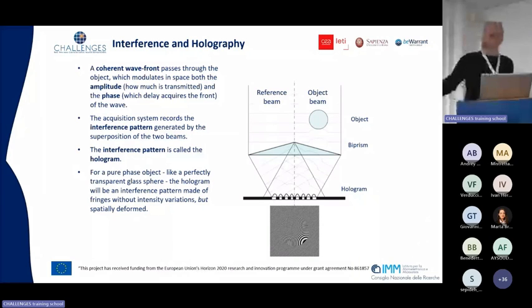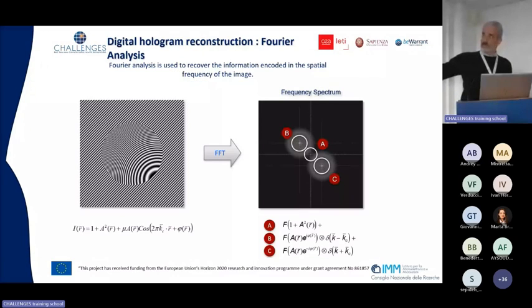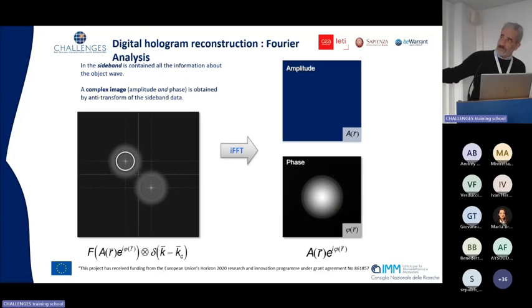What do we do in this case? We do a Fourier analysis of this pattern. We can represent it in a frequency spectrum. Since we are interested in phase, we can filter this diffraction pattern, get rid of the amplitude part and just take the phase, which we can find in the sideband.